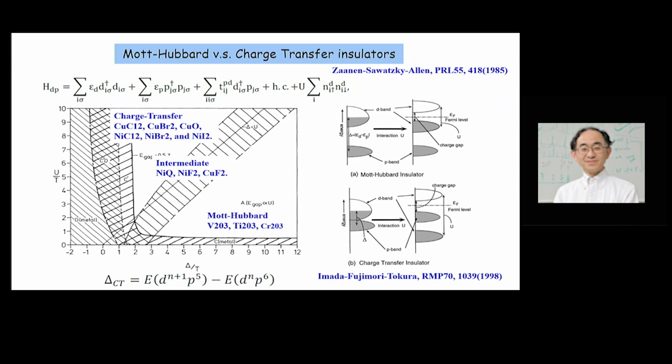This 2p orbital is doubly occupied, so it becomes inert, namely, this is the 2- ionic configuration. And then you have singly occupied d orbitals. At the Mott transition, this density of states will split into the lower Hubbard band and the upper Hubbard band. This is the usual picture described by the Hubbard Hamiltonian I just mentioned.